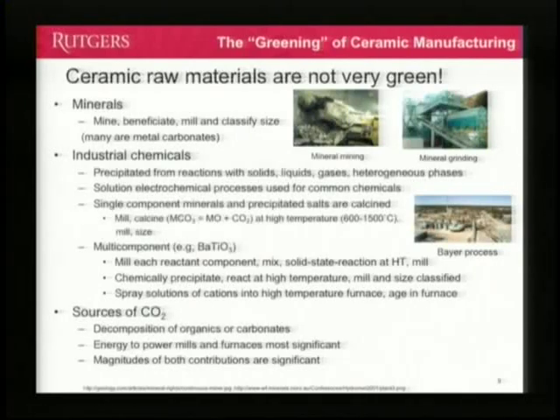So we go look at something like barium titanate, very frequently made from a material that's either from carbonate or oxalate origin. There's roughly half of its, all of its weight loss is pretty much CO2 emissions. And then, like I said, you burn almost as much petroleum or some kind of hydrocarbon to actually make this final product. And we're only in the powder stage at that point.